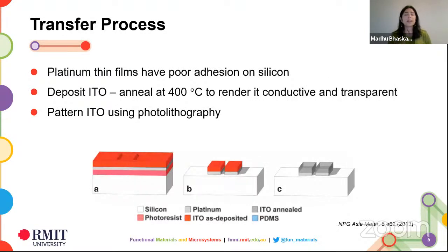The next two slides will give you an idea of the transfer process which we developed within the group. This process was patented, and that has led on to other studies and also some industry collaborations. The entire premise on which this transfer process works is the fact that platinum does not stick to silicon. If you use platinum with silicon, you generally use an adhesion layer. But in this case, we didn't want the platinum to stick well to the silicon because we're using the platinum as a transfer layer. So we put down the platinum thin film on silicon, but let it adhere quite poorly.